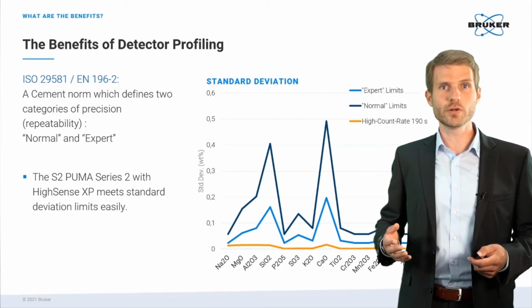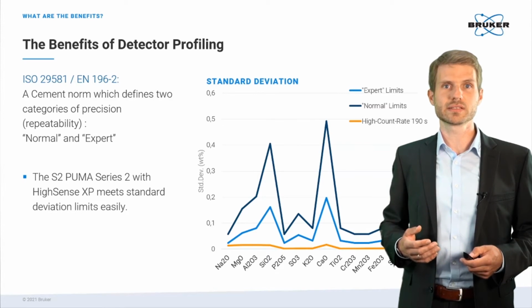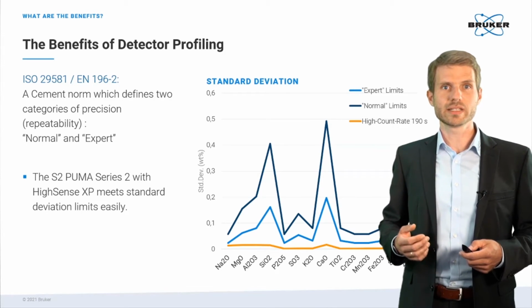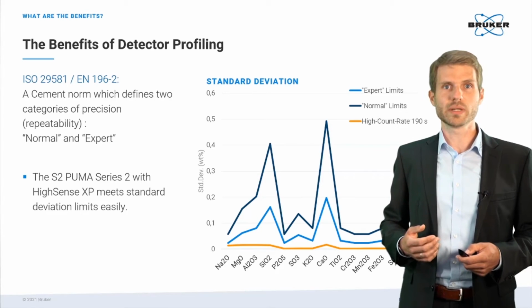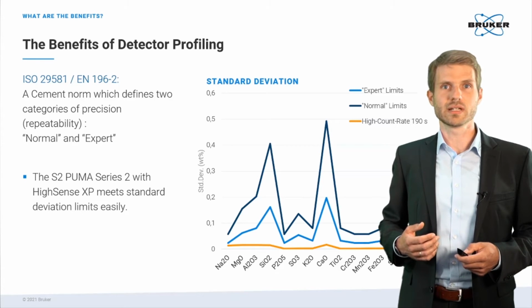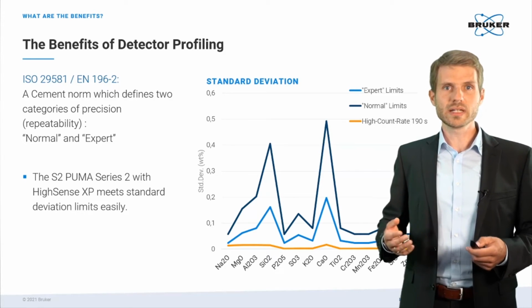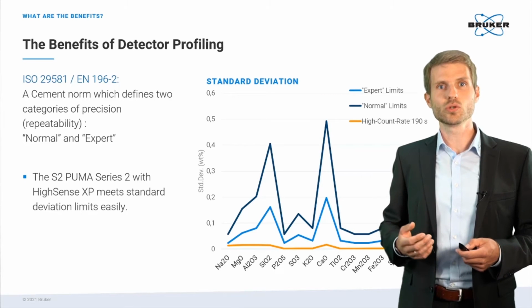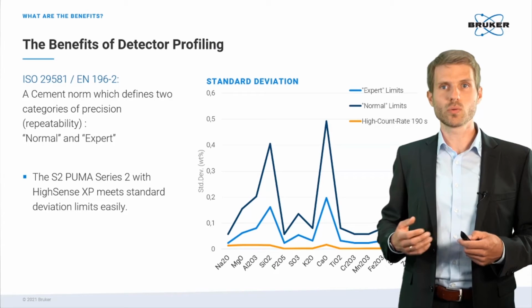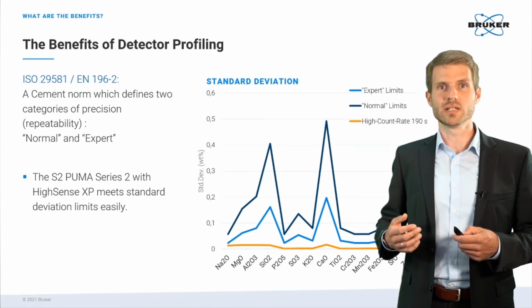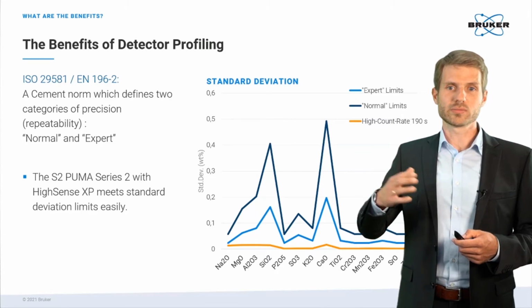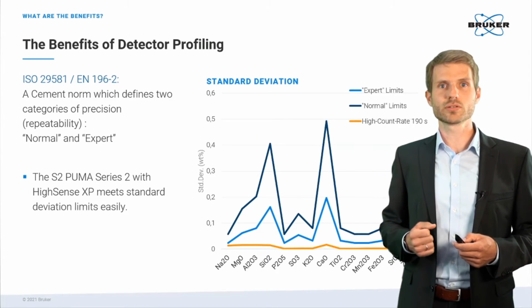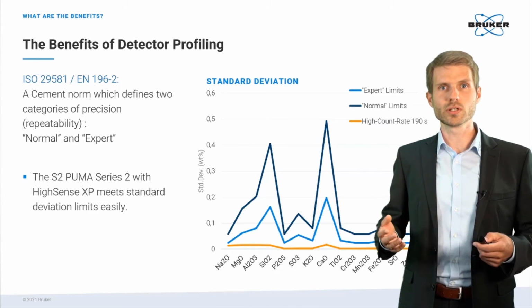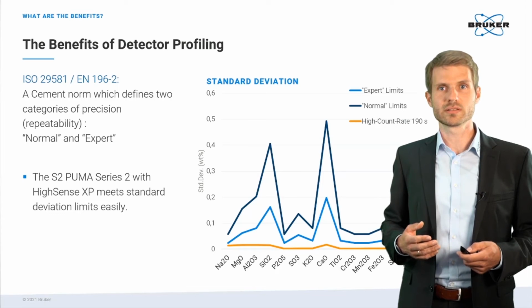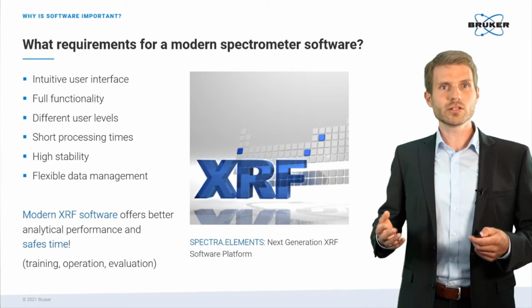Now we can go one step further and compare the results obtained with the HighSense XP and the high count rate for the 190 seconds with the limits of the cement norm ISO 29581 or the European norm, basically nowadays valid, the 196-2. Clearly, we can see that with these settings and the new HighSense XP and our high count rate, we are well below the limits of this norm, as well as the expert limits. So this shows again the suitability of the PUMA with the new equipment for cement and related applications, such as limestone. Now let's talk about software.